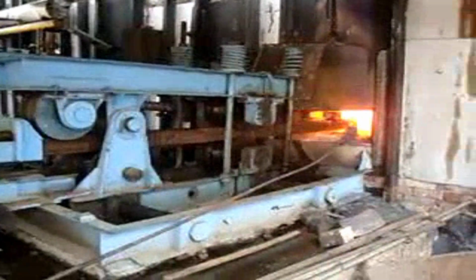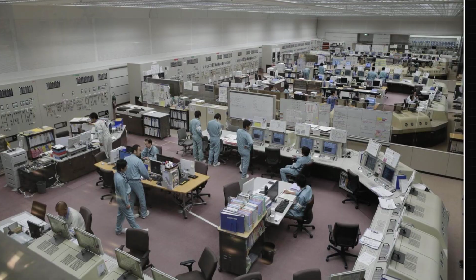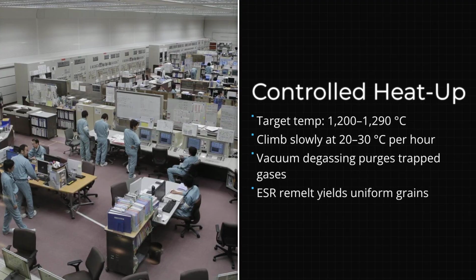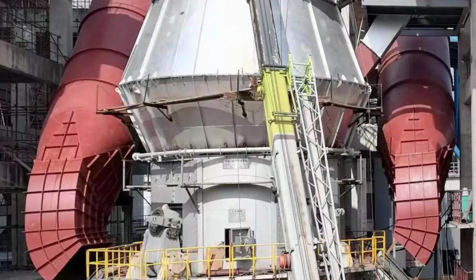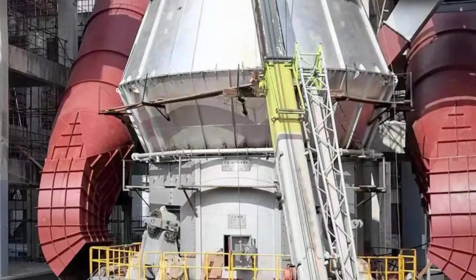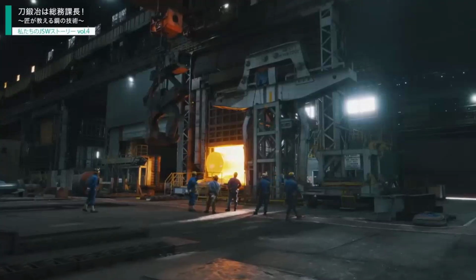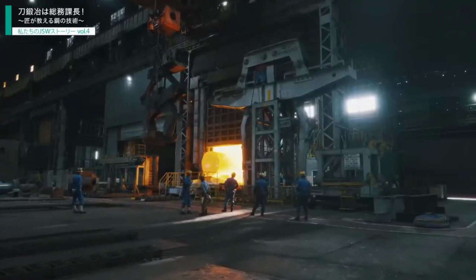The ingot then heats slowly to avoid thermal shock cracking, reaching temperatures between 1200 and 1290 degrees Celsius, at rates of roughly 20 to 30 degrees per hour, with soak times of 45 minutes to an hour per inch of thickness. Heating a single ingot can take 24 to 72 hours per cycle, and that is before any forging begins.